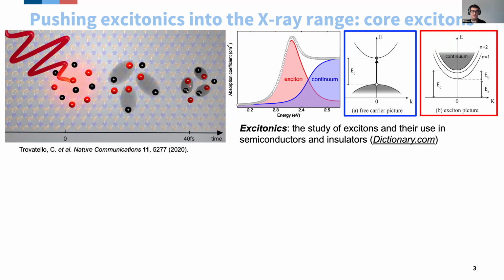And there is a very easy way to form these excitons. It's by shining light on a semiconductor with an energy in the light field that's above the bandgap of the semiconductor. Initially, this will form a bath of electrons and holes. They will not be coulombically bound at the beginning because there is a very efficient screening between these different charge carriers. But as time progresses, Coulomb pairs will start to form these excitons, and this is happening on ultra-fast timescales. So in tens of femtoseconds, you have an exciton population that's formed in your material.